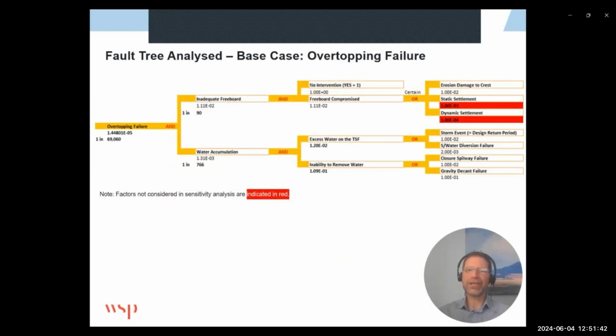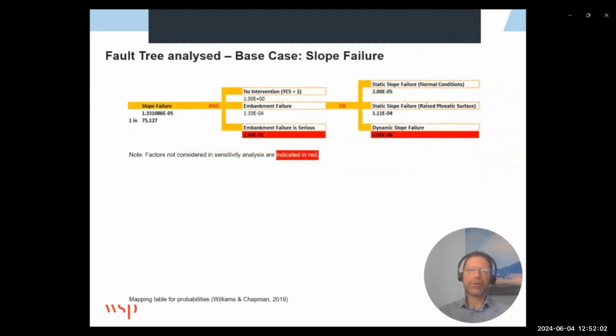The excess water can be a result of a storm event in excess of the design period, or stormwater diversion failure. And the inability to remove water can be due to closure, spillway failure, or gravity decant failure. If we look at slope failure, that can be due to no intervention, an embankment failure, or a serious embankment failure. Then we can also have embankment failure as a result of static slope failure under normal conditions, static slope failure under raised phreatic surface, or dynamic slope failure.